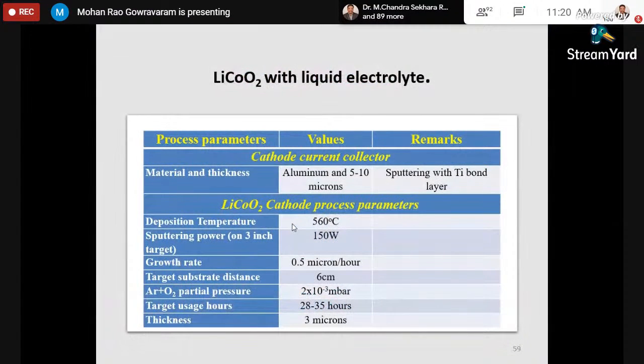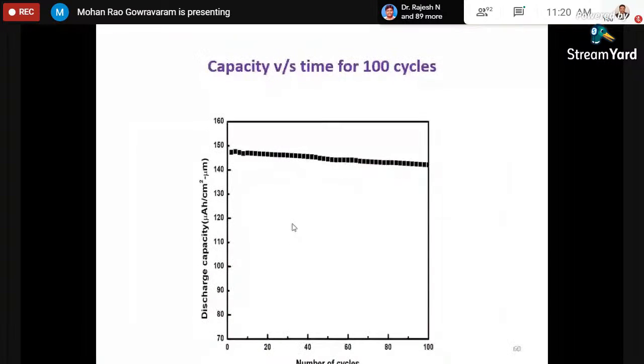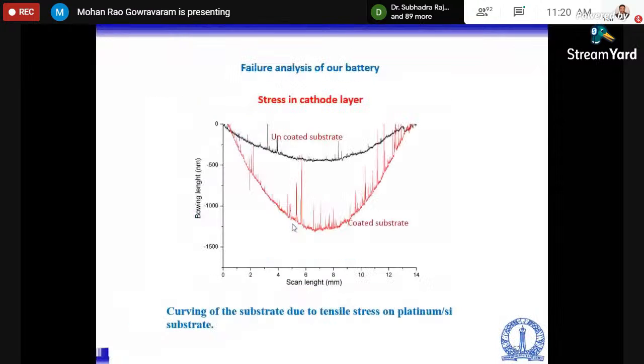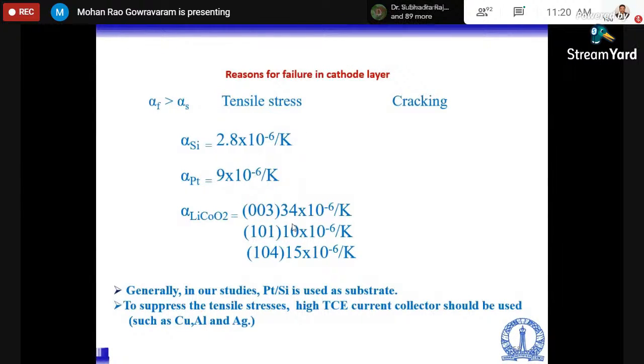Now you test your lithium cobalt oxide with liquid electrolyte. Now what is done here is that we found out that if you are using aluminum, which has got thermal expansion coefficient, which is in between that of your platinum and lithium cobalt oxide. That means it acts as a buffer agent. So we deposited a layer of aluminum across this and then deposited lithium cobalt oxide. But the problem is that when you deposit aluminum, then you cannot heat it to very high temperature, not more than 450 degrees. So your capacity will little come down.